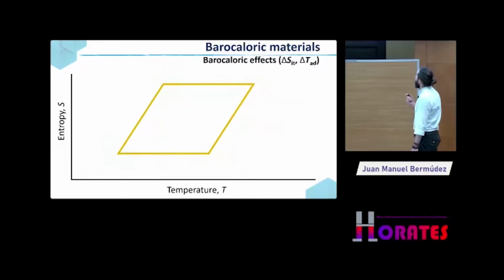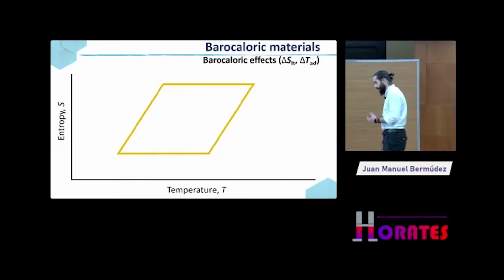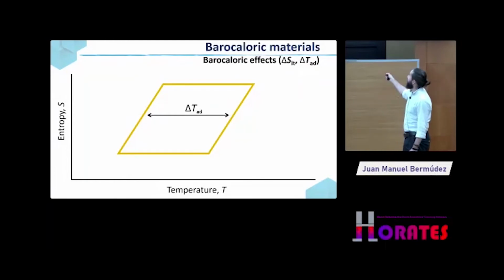So from this Brayton cycle, we can extract two important parameters in order to characterize and identify the caloric potential or the cooling potential of our materials and compare them with other barocaloric materials. And these two parameters are, on the one hand, the adiabatic temperature change of the material, and the other one will be the isothermal entropy change.